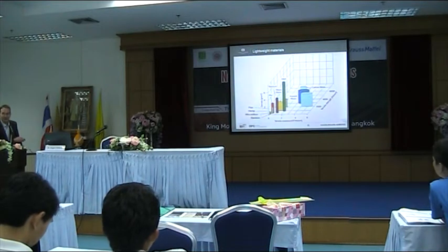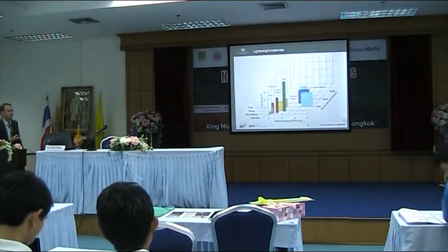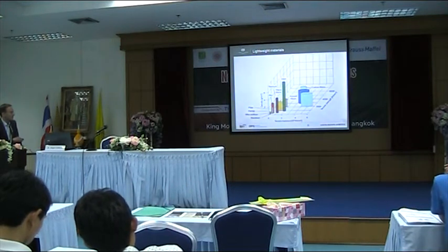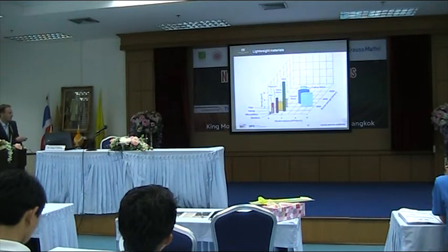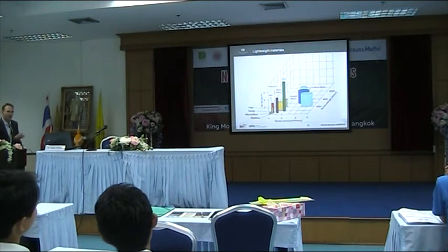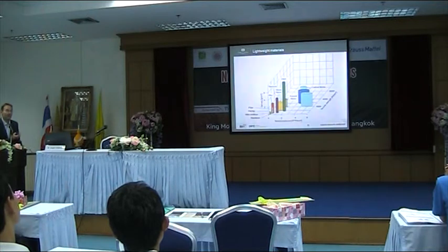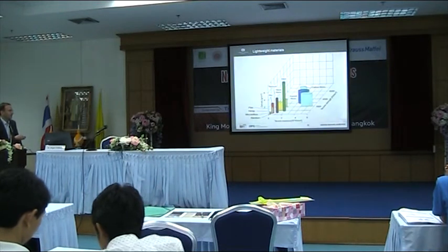But steel, of course, has a high density, so it's not something you can take for classical reinforcement for lightweight construction. So you see, of course, the overall tensile modulus and tensile strength of some typical natural fibers are not so good, but the density is really low. So this is something you always have in mind: the property in relation to the density. This is what we call a lightweight degree. Of course, not having in mind the costs to produce the part, but this is something we always have to look at.